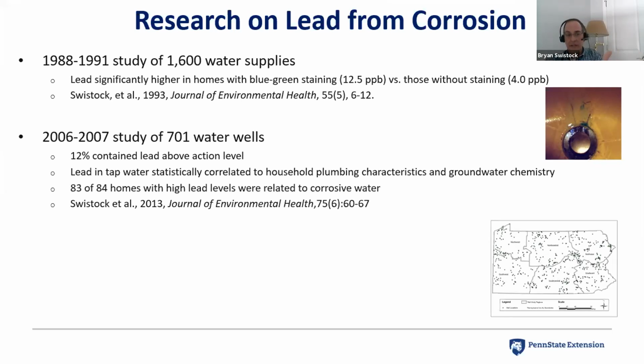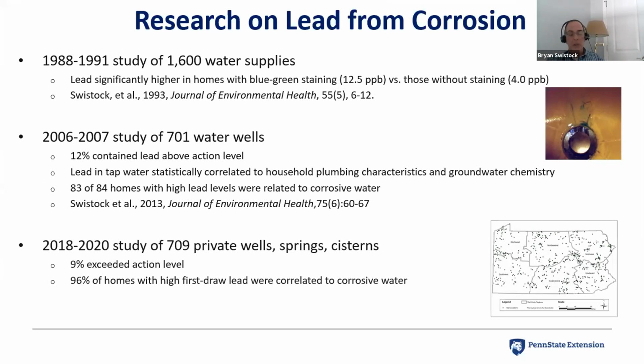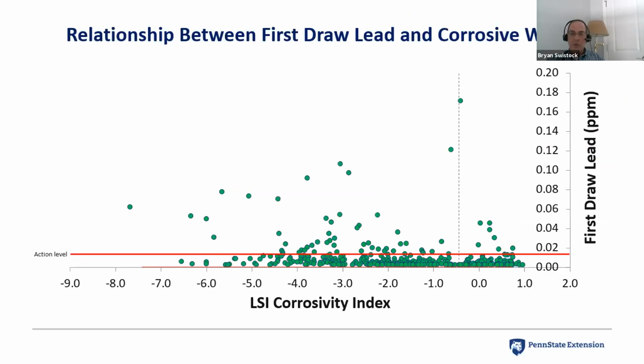Another study found statistical correlations between the type of household plumbing, the chemistry of the groundwater, and the amount of lead. In that case, 83 out of the 84 homes that had high lead, we could definitely say were coming from corrosive water. Only one was even questionable about whether it was corrosive water. In the most recent study, we found 96% of the homes we were able to correlate specifically to corrosive water. So there's absolutely no doubt it is the predominant source of the problem.